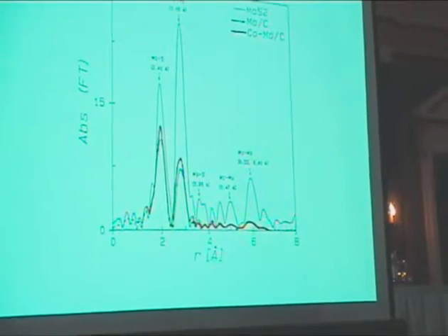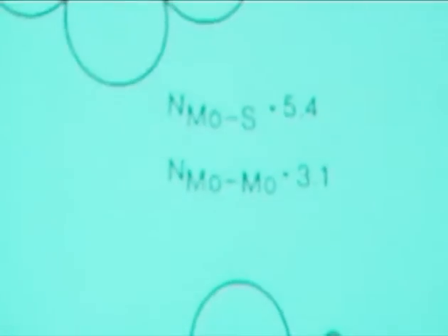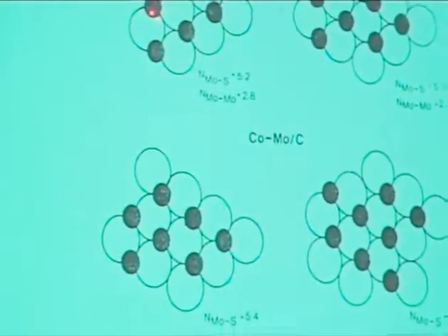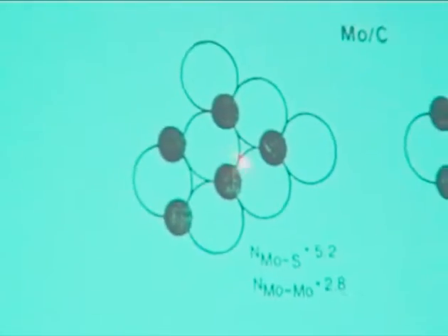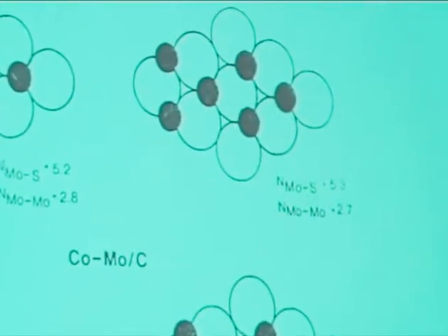And this shows immediately that we must be talking about small MoS2 particles. Because in the small MoS2 particle, the molybdenum has sulfur neighbors, and maybe it has a next neighbor, which is that molybdenum, and then it looks like it has no neighbors anymore. So it looks like, from EXAFS, the crystallites must be extremely small. For instance, as small as this. This could explain it. Suppose you had, and now my top part of the Belgian waffle is taken away. So you're looking at the big balls, which are the sulfurs, and the small ones are the molybdenum cations. And you see that, for instance, this molybdenum is having 1, 2, 3, 4 molybdenum neighbors. This one has only 2.